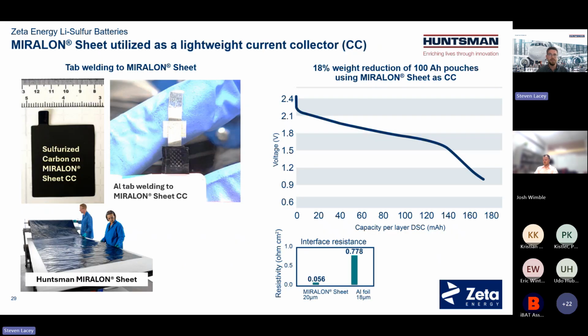Now, from a sheet perspective, this is also very unique because I want to highlight that they were able to tab weld directly to our MIRALON sheet with ease. And from this, they also showed that if they replace aluminum foil with MIRALON sheet, you can have an 18% weight reduction in their 100 amp hour cells. And from this, we have a very standard voltage profile. However, the interface resistance significantly decreased with MIRALON sheet versus aluminum foil.